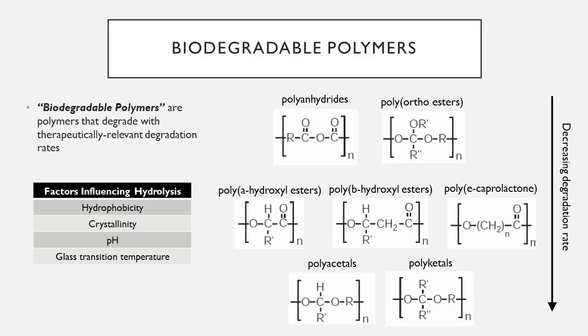And the same thing is exhibited by polyorthoesters, right? Orthoesters degrade at slightly slower rates than polyanhydrides. Polyanhydrides are on the order of days to just weeks, and polyorthoester is a little bit longer than that. But it exhibits the same properties. It's slightly hydrophobic, so it's more hydrophobic than it is hydrophilic. So it also exhibits the surface erosion profile that results in a near zero order release of drugs that are encapsulated within.